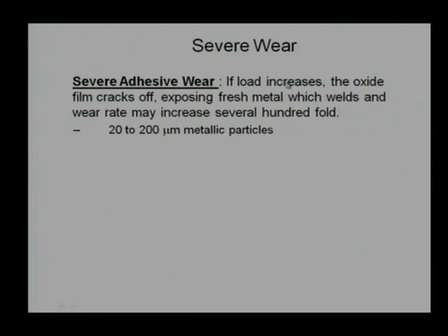In this case, we are saying that if the load is increased, it is weakening the oxide layer. Obviously, when the load is increased and the surface is rough, the asperities will penetrate the surface and tear away the oxide layer, and virgin, nascent material will be exposed to the surface which is transferring the load. It gives more opportunity for adhesive wear, more and more cold junction formation, and if we introduce friction force, tangential force, wear rate will be very high.